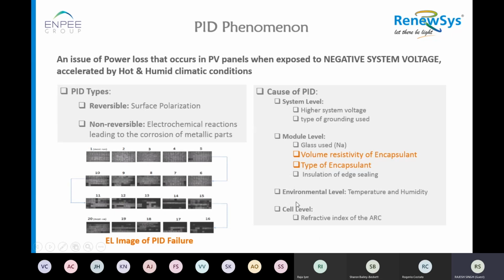In that case, if I focus only on module level PID control, it is actually caused by low volume resistivity of the encapsulant, or maybe the type of encapsulant. So at module level, it could be controlled by reducing the conductivity or increasing the volume resistivity. These properties are inversely proportional. Or we can choose an encapsulant which is non-polar in nature, and that is what POE is, as we discussed, where its volume resistivity is higher naturally.